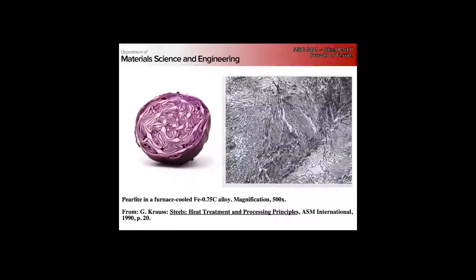We have these layers of cementite that grow, right? We nucleate, and then we just sort of grow layer upon layer, sort of like an onion, but much more convoluted, right? So you can still peel the leaves off the cabbage, right? But they're much more intertwined than the layers of an onion, right? And it's also a good analogy because even though the individual layers are all crinkly, cabbage is still round, right? So pearlite forms these nice round equiaxed colonies, but this crazy convoluted structure, right?